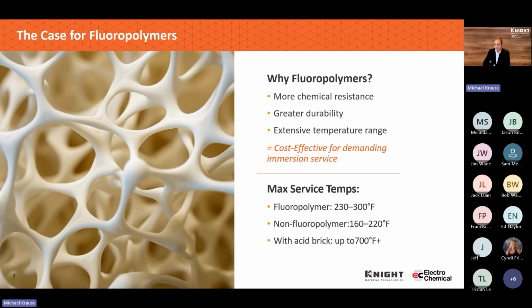Their problem was that the existing tank wouldn't hold up to the 70% hydrofluoric acid. They'd have to put a new and different alloy vessel in to do that, which they were willing to consider. The problem they faced is that that alloy wouldn't hold up to the dilute 49% HF concentration. And here, what we found is by switching to a PFA lined carbon steel vessel that wasn't much more costly than the alloys they were looking at, they were able to handle both the 49% and the 70%. It gave the customer more flexibility.